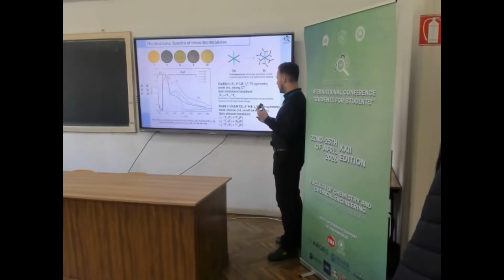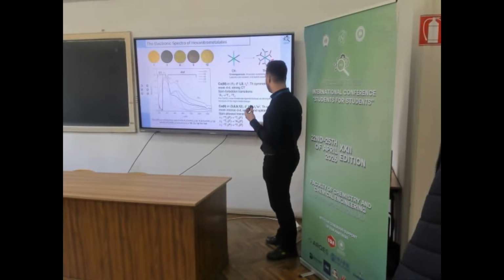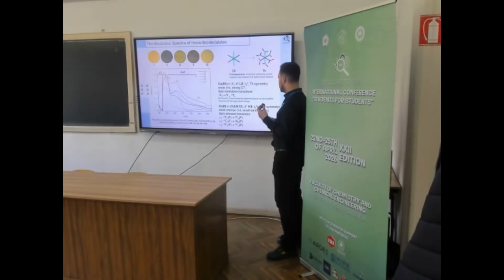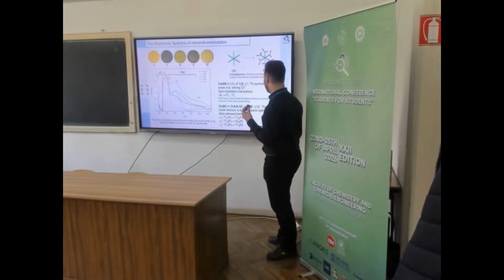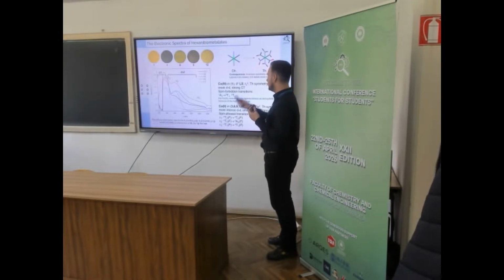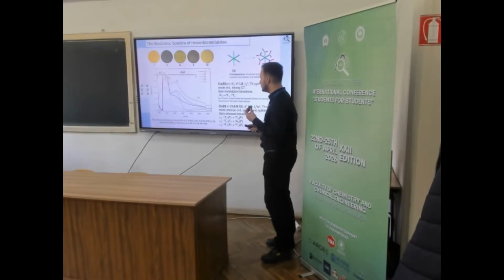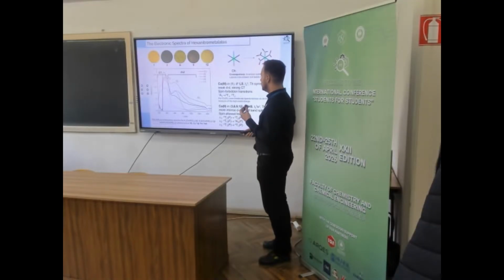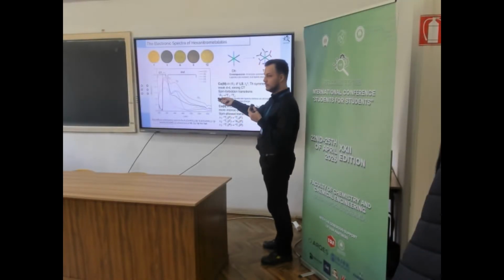In all the other complexes, we find the cobalt in high spin. Because of this, we now have some spin-allowed transitions and further reducing of the symmetry, which makes the bands more intense. One thing I didn't mention is the charge transfer bands at 200 and 400, which overlap with the first d-d transition, which makes the complexes colorful.